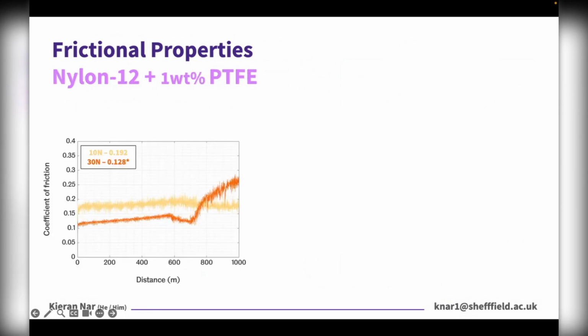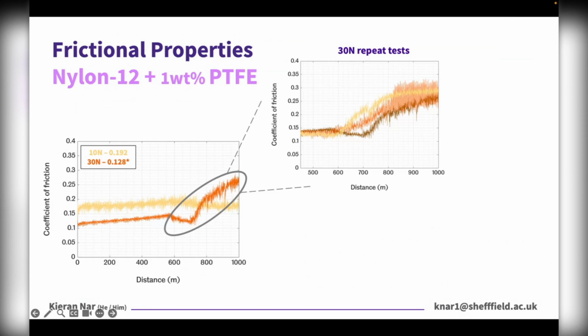So this is that coefficient of friction trace just blown up a little bit, and I'm sure you're all wondering what's going on with that big spike in friction. Well, the consistency in which PTFE PA12's lubricating response broke down, both in terms of applied normal load and moment of occurrence, suggests that this material experienced a frictional heating related failure.